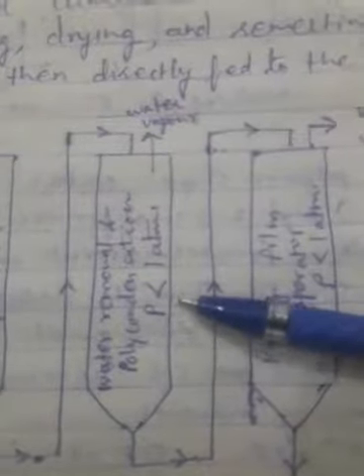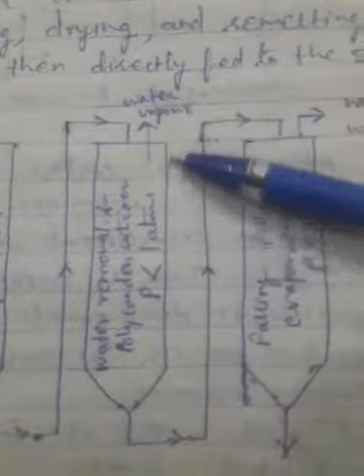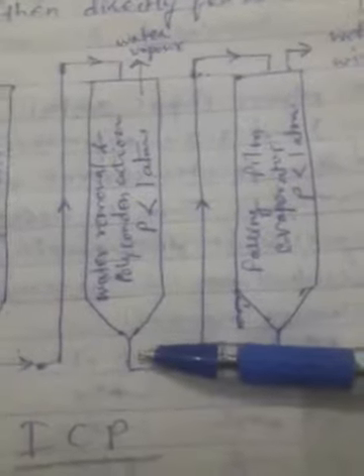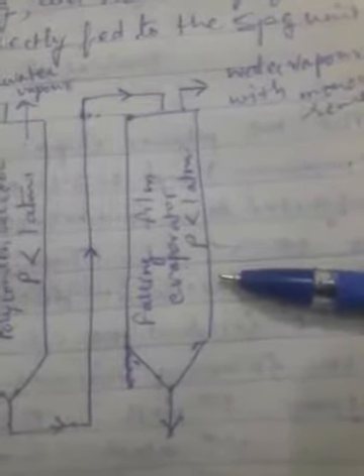Water vapor is removed in the polycondensation reactor. The molten mass — nylon 6 polymer still containing small quantities of unconverted caprolactam, oligomers, and some water — is transported to the next vessel: a falling film evaporator. The molten mass moves in a very thin film from top to bottom, and water vapor and monomer are removed.